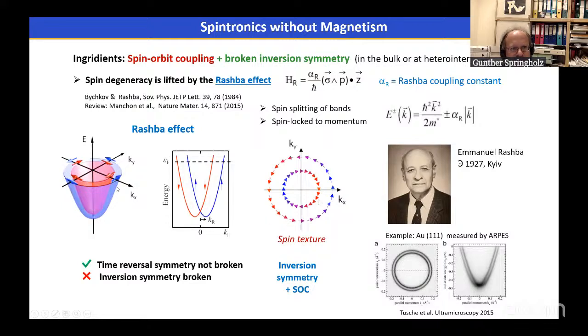If you look here, we make a cross section at constant energy, and we look at the spin texture, the spin orientation at different in-plane kx and ky points. We see we have two concentric rings formed by these two bands, and in each of these rings, the spin polarization has a chiral structure. So the spins point here to the right, and if we go around 180 degrees, it points to the left, and then at 360 degrees again to the right. And in addition, these two rings of the two branches have opposite chirality of the spin texture.